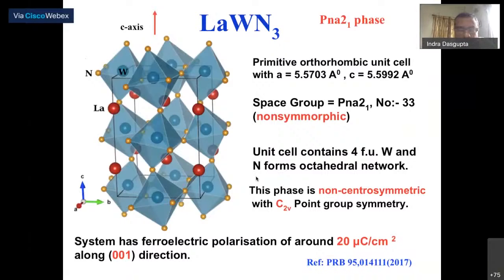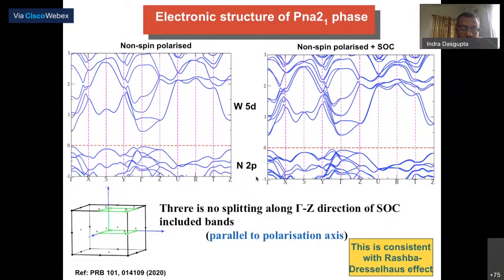With this, we went ahead and did what is known as a non-spin polarized band structure calculation for LaWN3. Lanthanum bands are empty, tungsten bands are empty, nitrogen bands, and what we are essentially going to focus on is the tungsten band, where the spin orbit coupling is expected to be strong. This is a calculation without spin orbit coupling, and you can see that there is no splitting. But as soon as you switch on spin orbit coupling, we figure out that the band starts splitting. Particularly, see the points as you move away from the Z point, or as you move away from the gamma point, they start splitting. They don't split along the gamma Z direction.